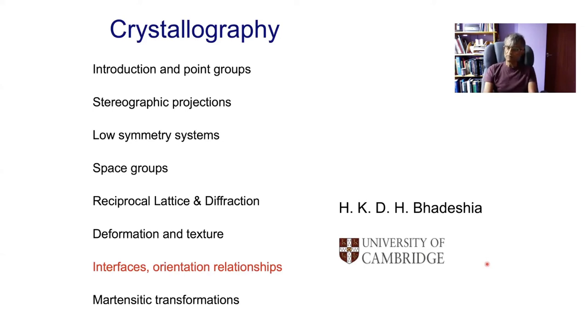My talk today is about interfaces and orientation relationships between crystals. Now, we sometimes imagine an interface to be a single descriptive term that describes the region where two crystals meet. Perhaps we imagine that there is some degree of disorder associated with that transition region. Quite reasonable assumptions. But interfaces, in fact, have a significant degree of periodic structure, a lot less than that associated with a perfect crystal, but nevertheless, a clearly defined structure.